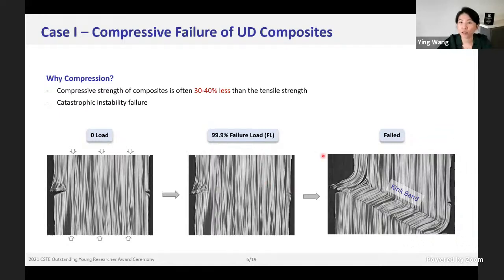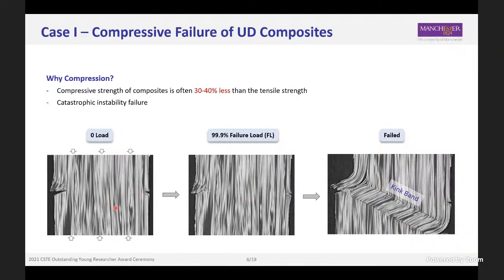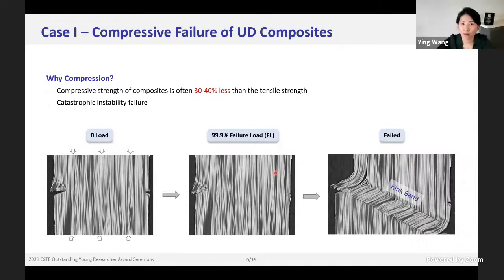It turns out to look very similar to the composite at zero load. So the deformation of the fibers is very small. So that makes us interested in understanding whether X-ray CT, the three-dimensional information, can help us to find some traces of precursors leading to the nucleation and propagation of kink bands. So that motivates us to do this study.